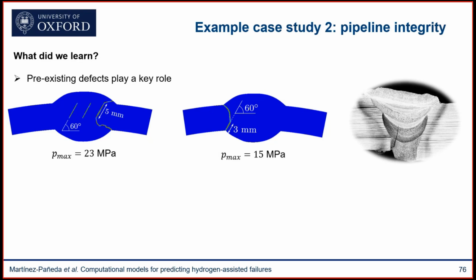And this is important because, first of all, those defects have been reported to exist. We know that these kind of defects along the heat-affected zone of this size are observed in welds. And second of all, because this is a critical pressure that is within the range that gas distributors are considering to transport hydrogen.